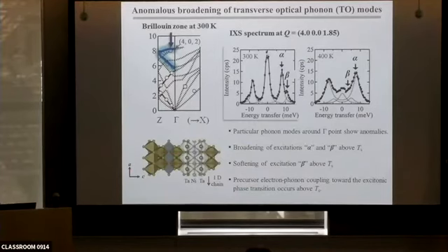That's the reason for the discrepancy between the energies of these modes. Raman sees the center of the Brillouin zone, while you're looking a little bit far away on the dispersion, and that's why they change in energy. If you propagate this back to Q equal to 0, at which energies are they?